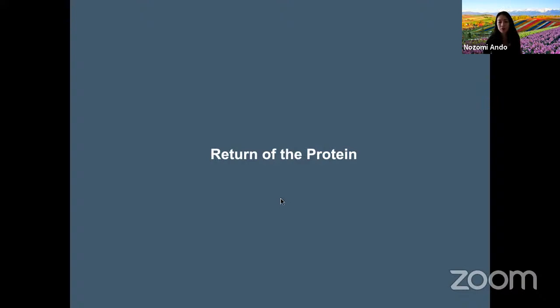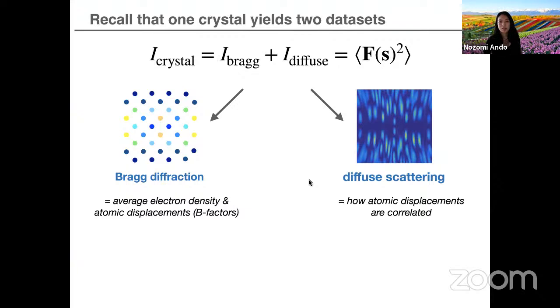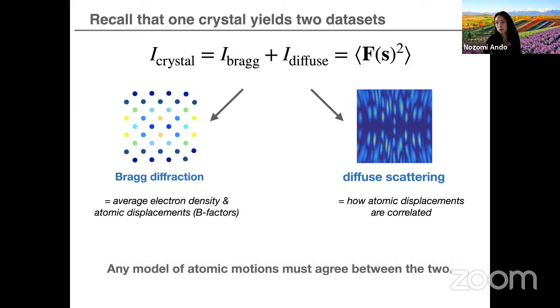And so before I tell the last bit of the story, just a reminder, I'm showing this slide again, that one crystal yields two data sets. There's a Bragg diffraction and the diffuse scattering. And any model of atomic motions has to agree between the two of them. And so what Peter Moore had said in 2009 was that if you refine your structure and you get B factors that are implicit of a certain type of motion, that also has to give rise to diffuse scattering that matches experimental scattering.